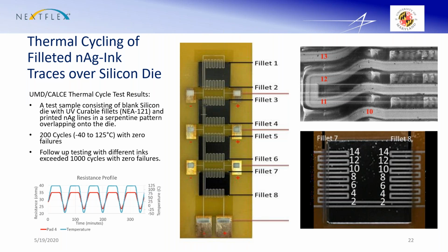Now this is something Brian alluded to. We worked with CALCE, University of Maryland. We were interested in the baseline reliability of it. Now we're using it for 3D structures, so we developed this little test coupon, and we have a blank coupon, a silicon blank that's about 5 mils high, 125 microns, and we aerosol jet printed these dielectric fillets. The dielectric fillets are made from a Norland material, NEA 121. It's pretty common.